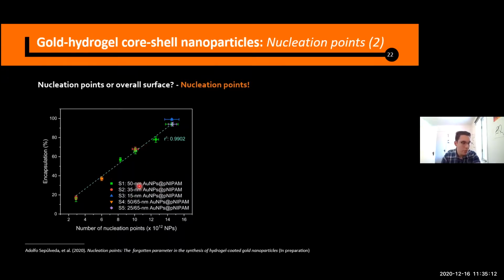To this end, we perform different polymerizations with different particle sizes by using 50 nanometer gold nanoparticles, 35, 15, and we also proved that we can mix these particle sizes, and we are going to obtain the same encapsulation yield if we control the number of nucleation points.